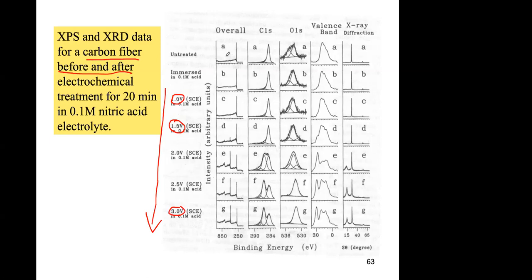So here is what you see, a spectra. It's an overall spectra, what we call a survey. So you see mainly the carbon 1s peak. When you start to oxidize the carbon, you start to see the oxygen 1s peak here. So this is the oxygen 1s peak formation, which clearly shows that you are oxidizing the carbon fiber. When you look closer in the binding energy region for the carbon 1s, you basically see one peak. But when you start to oxidize, you start to see these shoulders. And that shoulder basically increases enormously. And these are basically carbon oxide formation.